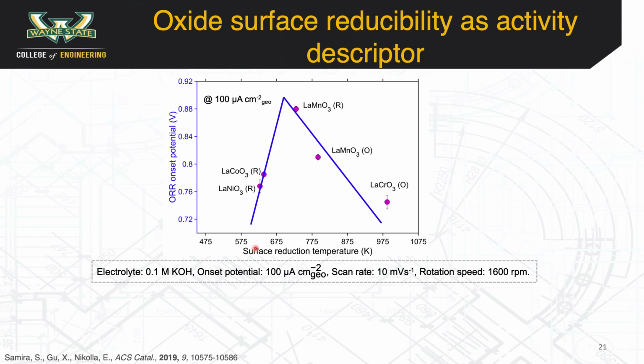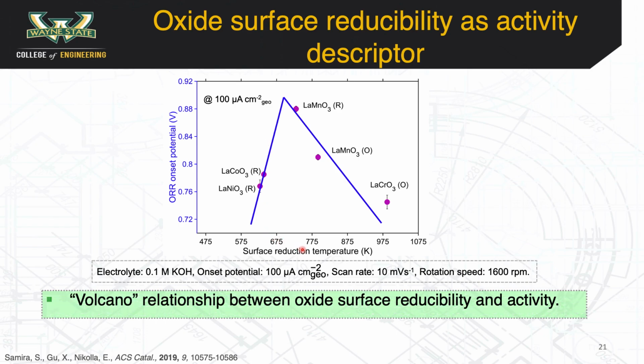One can then use the empirically measured oxide surface reducibility in terms of surface reduction temperature to describe the empirically measured electrocatalytic activity of these oxides. A volcano type relationship is observed between the surface reduction temperature and the ORR onset potential. Oxides on the left leg of this volcano are limited by weak adsorption of reaction intermediates, while oxides on the right leg are limited by strong adsorption of oxygenated intermediates.